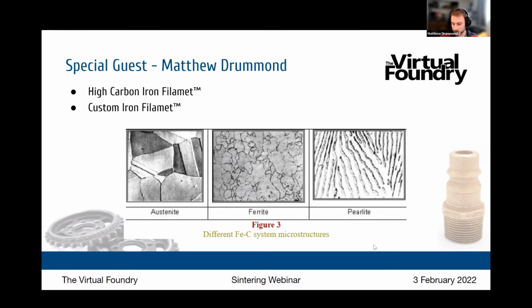I was there for 16 hours yesterday, and that was just for sintering. I debinded the previous day. So that's one nice thing with the high carbon: I debinded the day before. I left it all in the crucible, replaced the carbon on the top, and then put it back in, slowly warmed it up again, and then put it right to the sintering temperature and sintered it. And I got pretty good results yesterday. I did about 1200 Celsius, which is about 2200 Fahrenheit, I believe. I did that for 3 hours. I did 4 flow rate cubes in there, and they turned out very well.